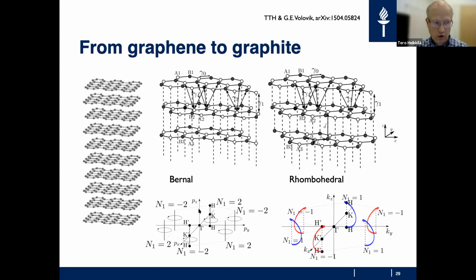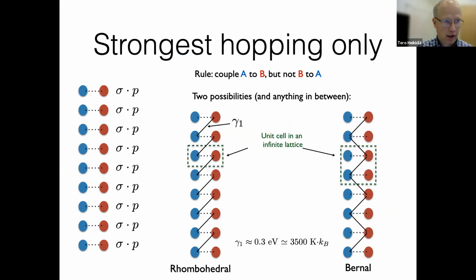Now, if you want to go from this bilayer to a higher number of layers, you have to make a choice. Either you do the so-called Bernal stacking, which is also called AB stacking, or you do the rhombohedral stacking, which is called ABC stacking. And the electronic spectra in these two cases look slightly different. In fact, both of them are nodal line semimetals. The Bernal stacked one contains lines which go mostly straight, whereas the rhombohedral one contains spiral lines. I will here only concentrate on the rhombohedral one.